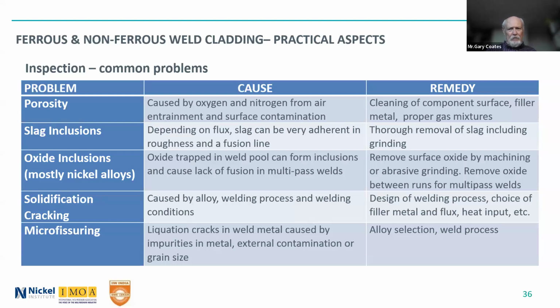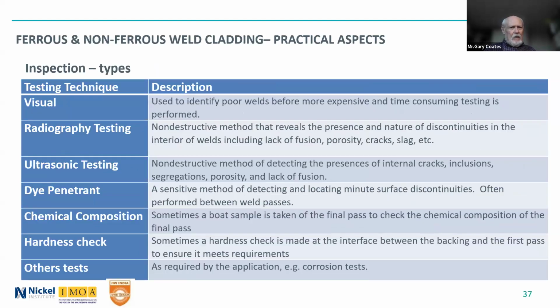Solidification cracking, and again with the nickel alloys it can be tricky because the cracks may not form immediately, so you have to be very careful there. And micro fissuring, again, it's making sure everything is clean. And there are some issues with grain size on certain of the high temperature alloys. Inspection techniques, well, that's no different than if you're doing a normal weld, you know, visual. If it doesn't look good, if it looks very rough, looks very dark in color, you need to almost start all over again and get it right the first time.